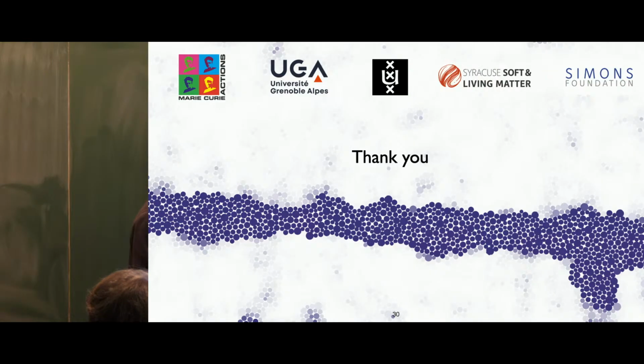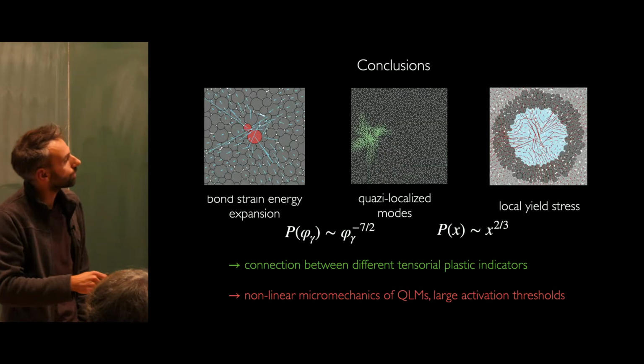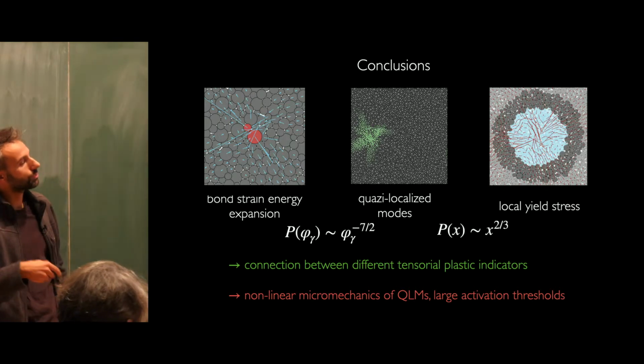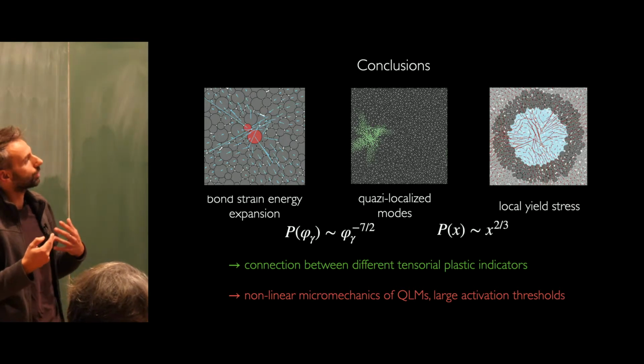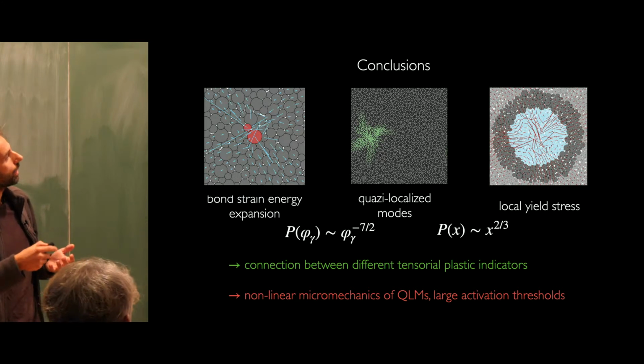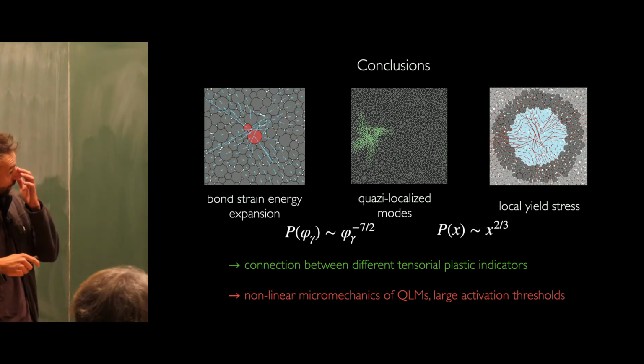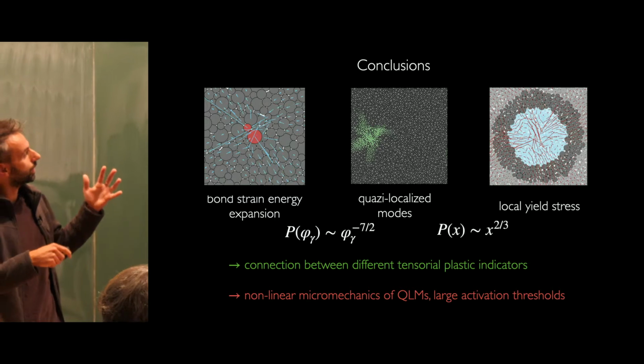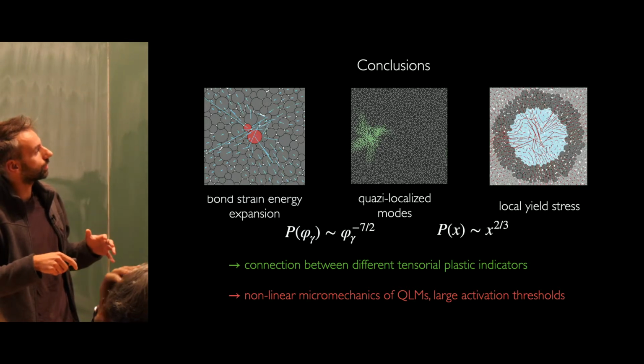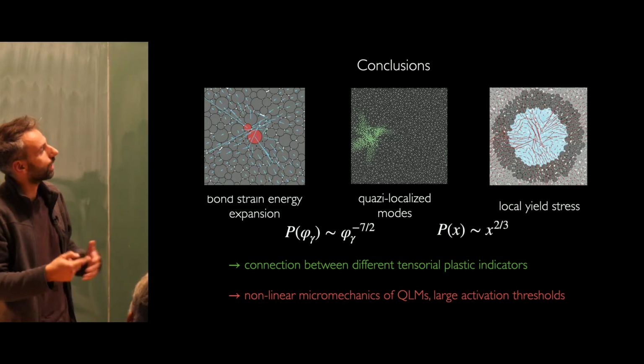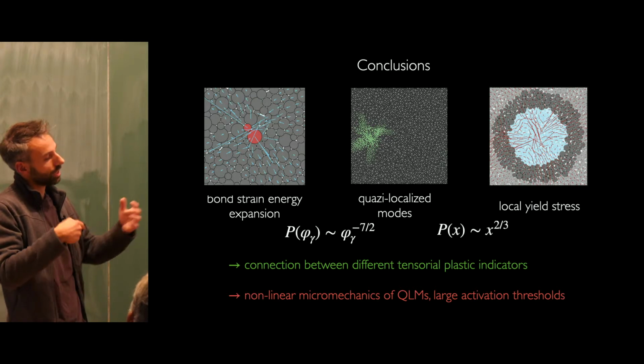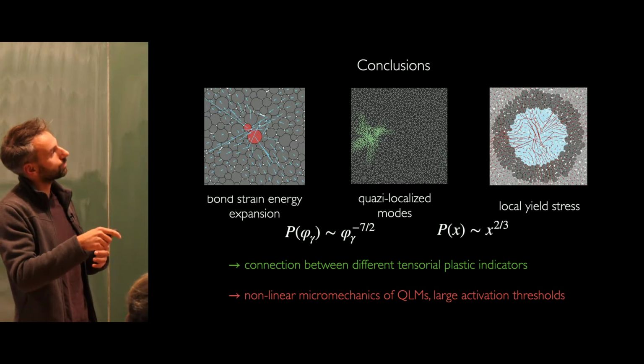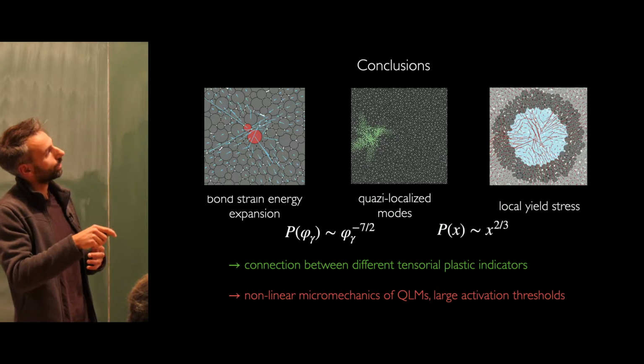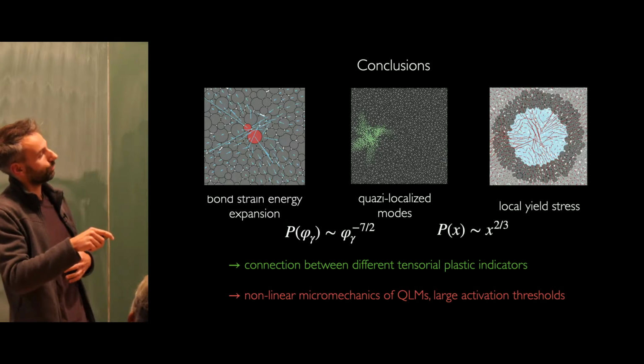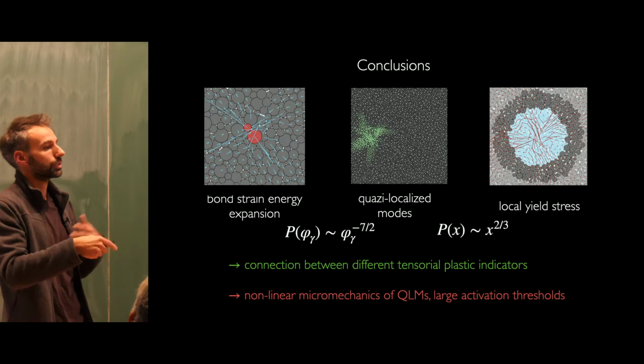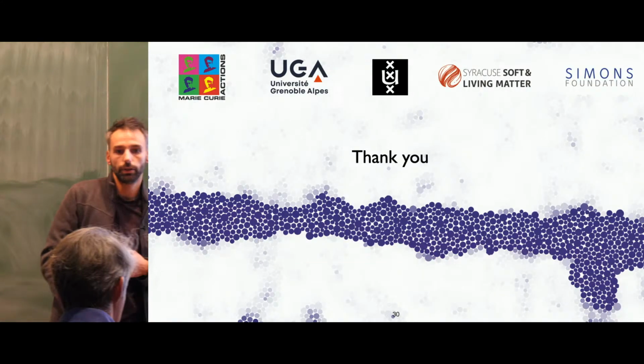So with this, I will conclude. I showed you some different structural indicators which are tensorial in the context of plasticity. I showed you some quantitative connection between bond strain energy expansion, quasi-localized modes, and local yield stress. And one of the things that we are going for is to go beyond the asymptotic regime, trying, from those tools, to work out the nonlinear micromechanics of soft modes to then start to get large activation thresholds. So, thank you.